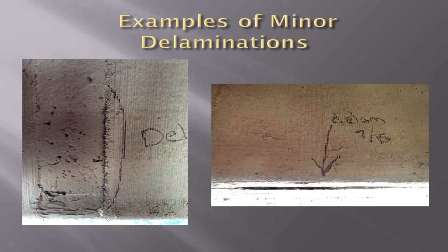From my markings there, you can see that there is actually a delamination. This is probably something that was incurred during installation. It probably hasn't grown. But you need to mark these delams and track them to see if they're getting any worse. Here's another delam on the edge of, it looks like we have some shear FRP in a U-wrap configuration going up the side of a reinforced concrete girder. We also have some flexural strip here, and the edge of the flexural strip is delaminated. This was most likely caused just during construction when they didn't put enough saturant underneath the strip.